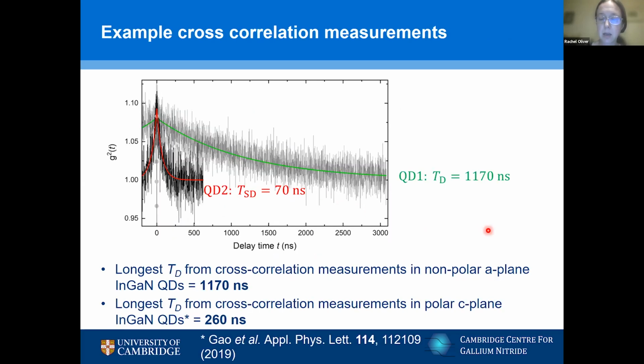Applying that in the non-polar A-plane quantum dots, I've just got two quantum dots here from really quite a large number that we have measured. And you can see these spectral diffusion timescales vary quite a lot. The shortest one we've measured is about 70 nanoseconds, and the longest is about a microsecond. Now, I think the level of variation here is down to just how defective this material is, and the defect density is quite inhomogeneous. So some quantum dots are much less influenced by defects than others, and that's still something we're thinking about and learning about.